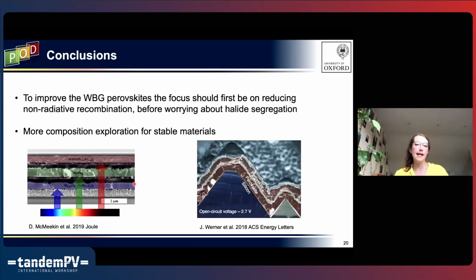So to conclude, in order to improve the wide bandgap perovskites in general, we really need to focus on reducing this non-radiative recombination. So really making just better materials to start with. There's also been suggestions that if we improve our radiative recombination, then the halide segregation actually gets better. So we get less halide segregation. And yeah, we're excited to look at more compositions to explore for these wide bandgap materials to make 2-junction or 3-junction tandem solar cells, whether that's all perovskites or silicon on perovskite.